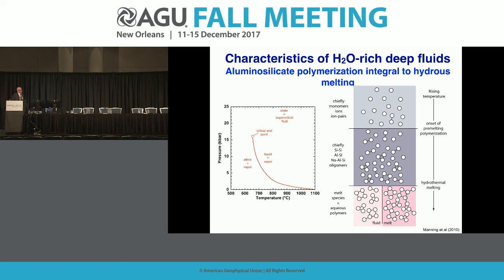And this is where this comes back to Bowen. If we think about the wet melting of albite here, we're used to thinking about, let's say, taking an isobar and increasing temperature, where albite in the presence of water will melt at this point. People rarely think about what's going on in the aqueous phase. But in fact, if you track what's happening in the aqueous phase, at low temperatures here, you have dominantly monomers, maybe a few dimers. As temperature increases and you approach the solidus, greater and greater degrees of polymerization are happening among the aluminum silicate constituents in the fluid phase.